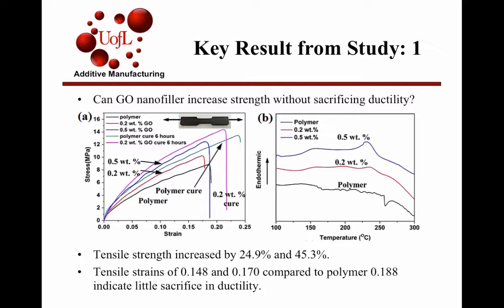And then this is the DSC I was talking about, which shows the polymer without the graphene oxide has a melt peak right around here, and so when you introduce the graphene oxide, it gives it more of a crystallization peak up in here, and that actually improves the structure, like I said, as they cure it over time. More crystallization occurs down here and allows it to become stronger after curing.